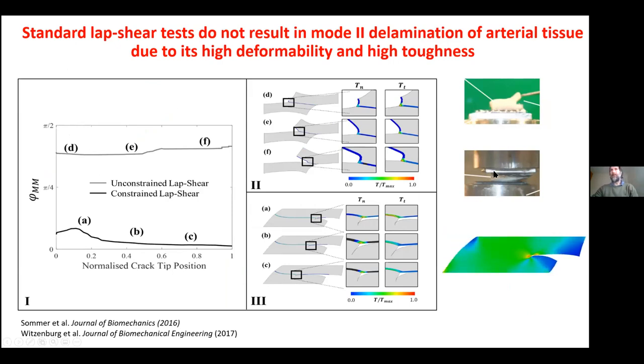And this is one from Gerhard Holzapfel and Gerhard Sommer. So basically you have a platen here, your artery is attached to the platen, and this is moved horizontally. And the idea is that you grow this crack in the horizontal direction under shear. Now, the problem is when we simulate this, if you look very closely at the crack here, what's happening is we need to get a huge deformation of the artery before the crack starts. So if you watch this carefully, when this crack starts, we're already at a 45 degree angle here.